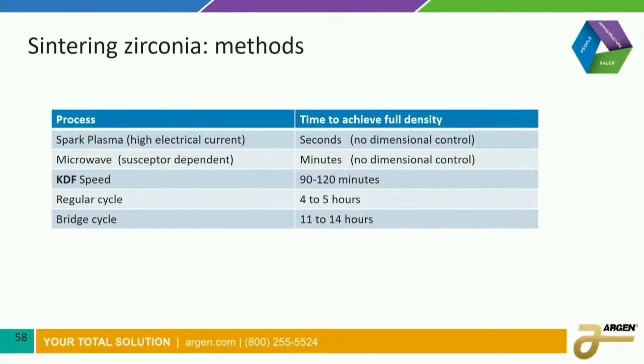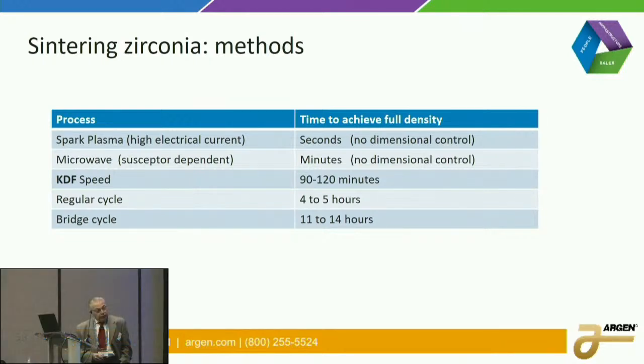Well, there are different methods of doing that. There's something called spark plasma, which is zapping it with a high electrical current. And you could achieve full density in seconds. Unfortunately, there's no dimensional control over it, so that doesn't help us. We can get the full density, but we're going to wind up with something like a potato chip. Microwave: you may remember about 10 years ago, people were trying to sinter zirconia in a microwave, and this depended upon what device you put it in. But again, you could sinter in minutes, but there was no dimensional control.